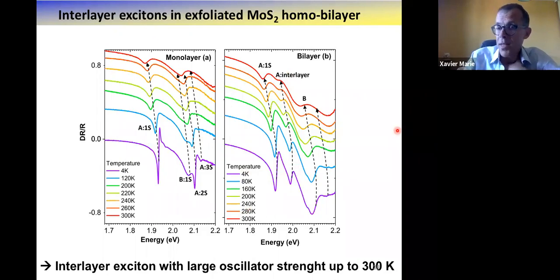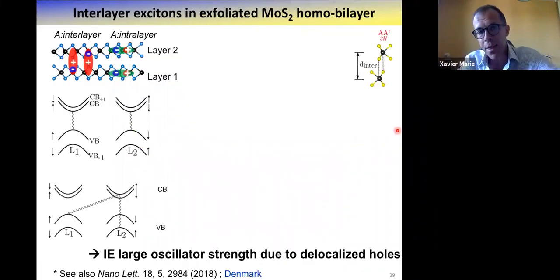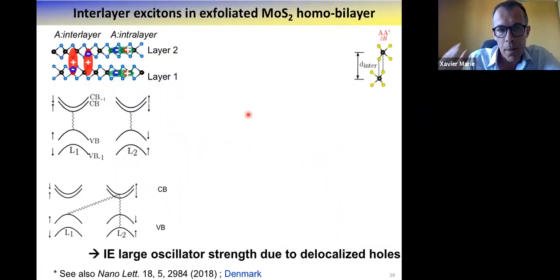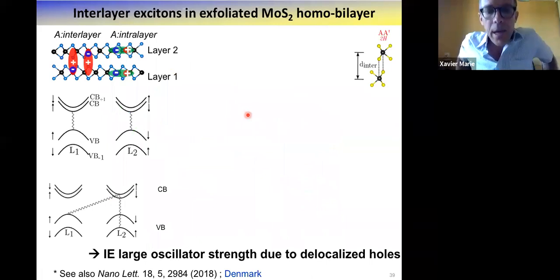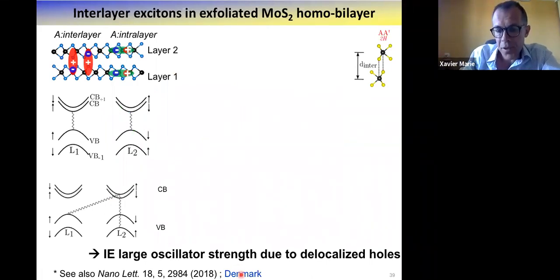So if it's an interlayer exciton, why does it have such a large oscillator strength? To understand this, we worked a lot with Yann Jaber in our laboratory, who performed ab initio calculations. And from this, we get clear information, and DFT calculations were also performed by other groups. Here we have schematics of the two layers, layer one, MoS2, layer two. So first you have the intralayer transition, electron and hole lying both in each layer. It corresponds for the A transition to these two transitions.